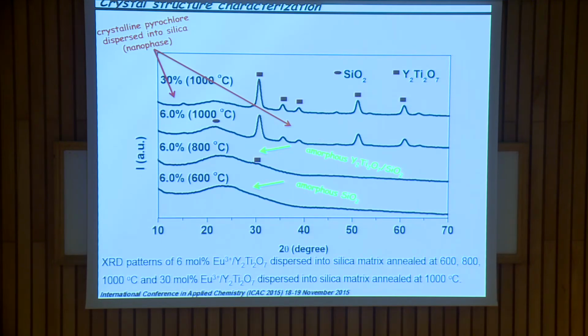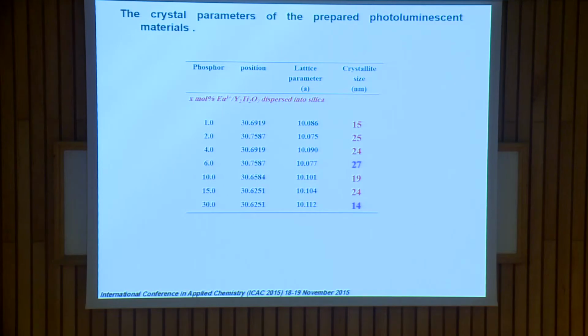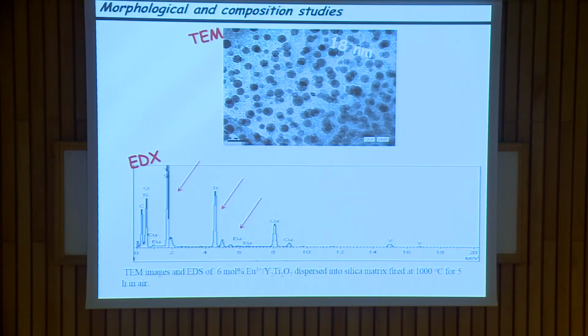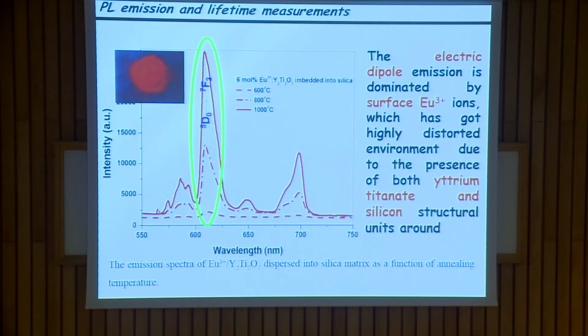This is our results. This is the XRD analysis for the europium-doped yttrium titanate co-doped into silica, and we can see that the XRD pattern gives a highly crystalline phase dispersed into silica at high calcination temperature. Also, the XRD analysis confirms that our particle size is in the nanoscale, and the TEM analysis confirms our results. The presence of europium ion is confirmed using EDX analysis. And this is the emission spectrum of the europium doped in our matrix, which gives a highly monochromatic light, as we can see from the photo, due to the f-f transition in the europium ion.